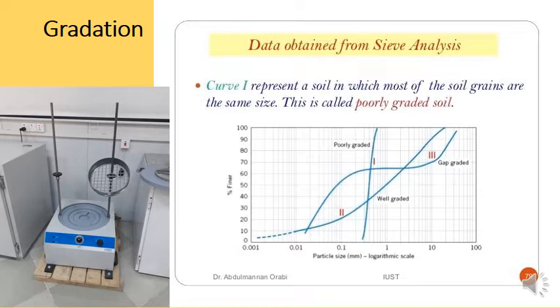So if you have a particle of aggregate which is let's say 35 millimeters in diameter, it's going to fall through the 40 millimeter sieve, but it's going to be caught by the 25 millimeter sieve. It's going to sit in that sieve. And after that, we can tell if it's poorly graded or well graded or gap graded by taking basically the percentage of aggregate which is caught in each sieve.